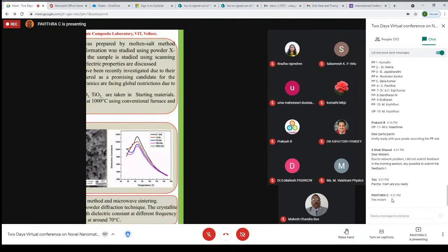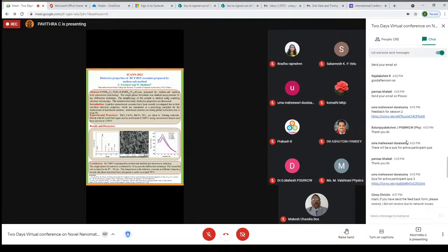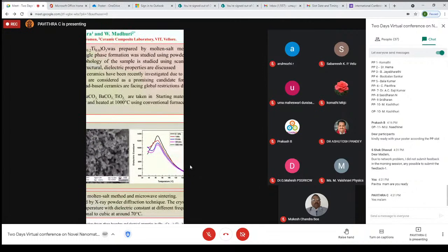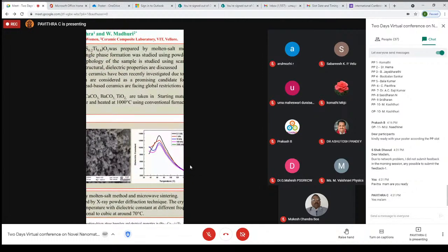Around 70 degrees centigrade, we get a shift in the peak. From that point, we can take it as the transition point of the material. From around 70 degrees centigrade, we have a phase transition from tetragonal to cubic crystal phase. This is very good for a lead-free material with a high dielectric constant. We achieved a very high dielectric constant, around 14,000 at 0.1 kilohertz frequency. A very high dielectric constant gives very good capacitance.